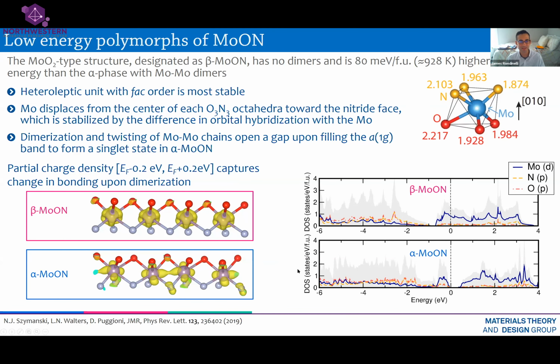And here is a picture of the charge density. So this is the real space distribution of the charge in molybdenum oxynitride. In the beta phase, the high temperature phase, what you see is that the charge over some window is localized on every moly site. Every electron that is derived from that moly is basically confined within some sphere to that moly site. When you dimerize, or these moly atoms get closer together, those electrons tend to be shared between each other.